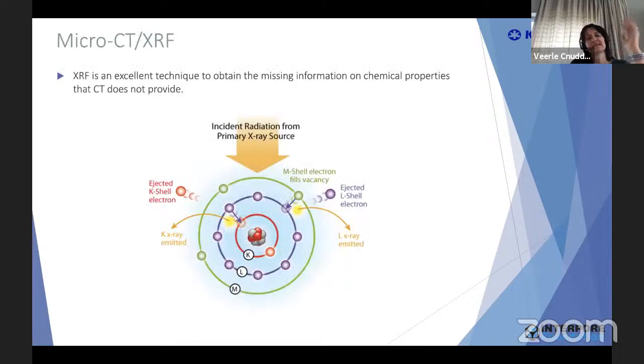Another possibility is combining micro-CT with XRF. XRF is an excellent tool to obtain the missing chemical information that CT does not provide. You also need an X-ray source, and then you collect the XRF signal, which allows you to get chemical information.